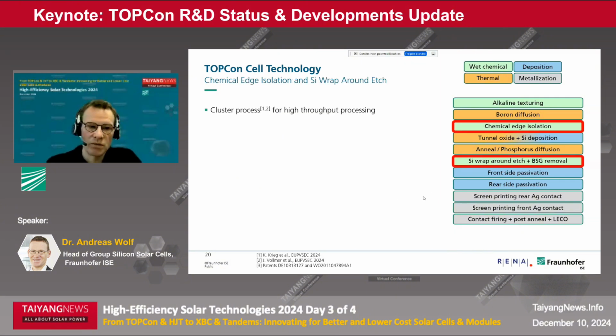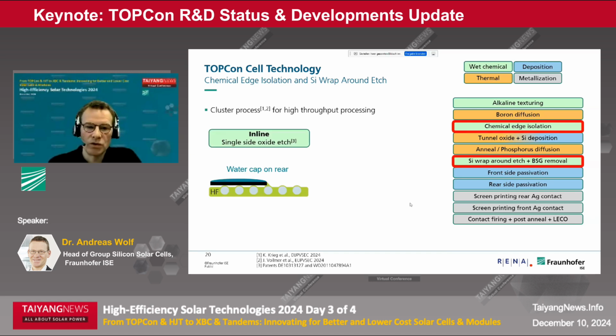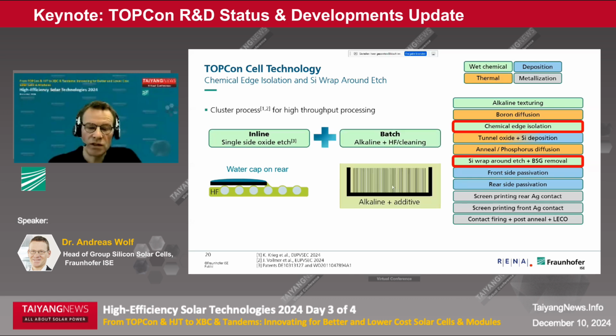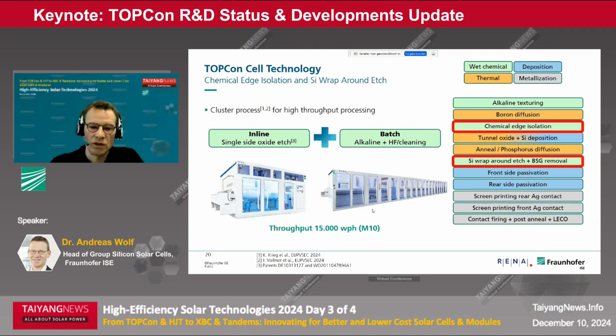For these 2 wet chemical steps, a cluster process has been established also by our industry partner RENA. This approach consists of first a single side oxide removal step where you, in an inline process, remove oxide on one side of the wafer and the water cap protects the other side, and this then facilitates the use of a high throughput batch process to etch the rear side. This gives you the possibility to use industrial tools with a high throughput to provide cost-effective wraparound removal in these 2 process steps.